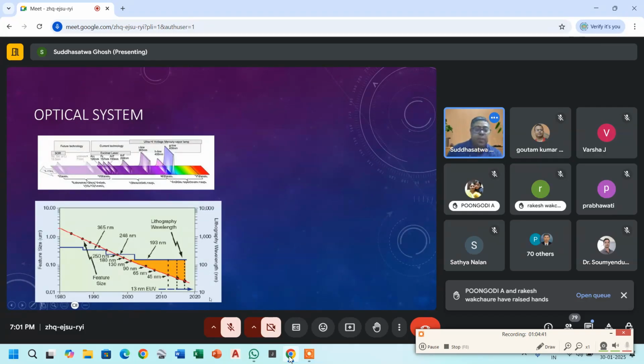And what you see in the figure below are the wavelengths that have been used over time. As we go down in the feature size, the industry moved to different wavelengths over a period of time. Initially, there was 365 nanometer, which used a broadband mercury vapor lamp. Then we moved to 248 nanometer, which uses laser systems, and this 248 nanometers could support features like 250 nanometers, 180 nanometers, 130 nanometers.